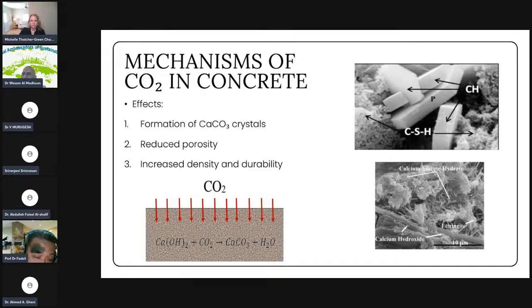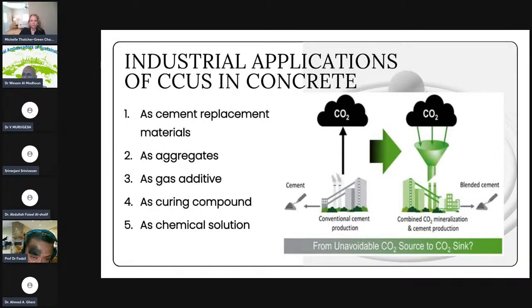So what I can say here is that the effort of injecting CO2 during the construction process or during the hydration of concrete or cement successfully reduces the issue of porosity inside the cement matrix, and at the same time helps the concrete industry and construction industry to reduce the impact of CO2 on the environment. The industrial applications of CCUS in concrete can be applied by using it as a cement replacement material. We can use the carbon dioxide as an aggregate. We can use it as a gas additive. We can use CCUS as the curing compound, and we can also use the carbon as a chemical solution.